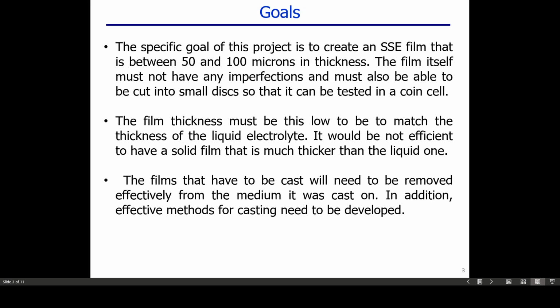The specific goals are that we're going to try to create an SSE film that is between 50 and 100 microns in thickness. The film itself must not have any imperfections, must not have any holes, must not have any impurities, so that it can be tested in a coin cell. And the film must be this thin to match the thickness of a liquid electrolyte, otherwise it would not be as efficient since it's so much thicker.